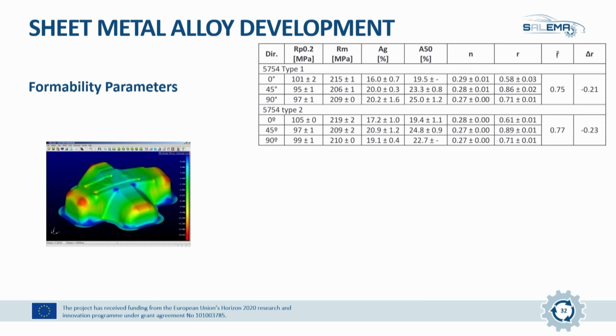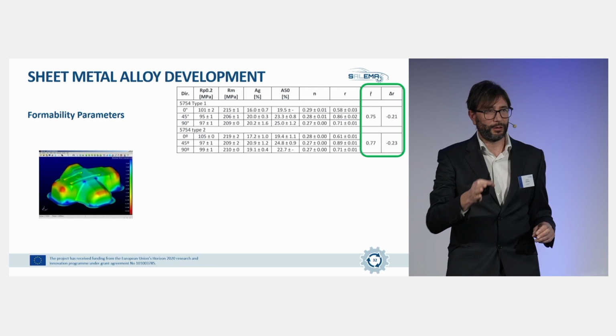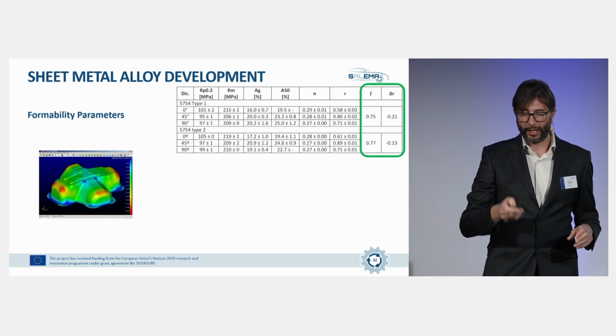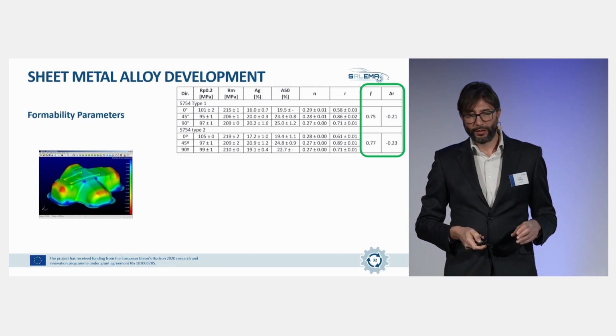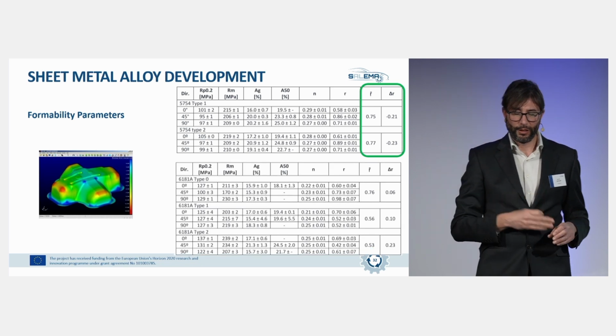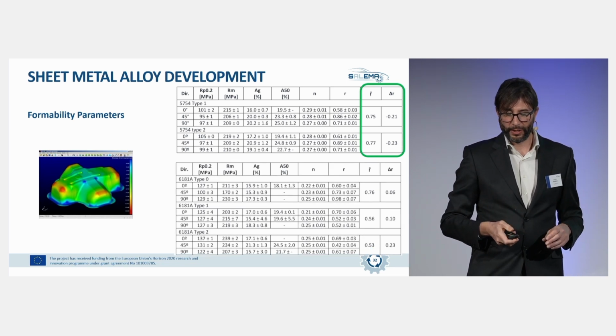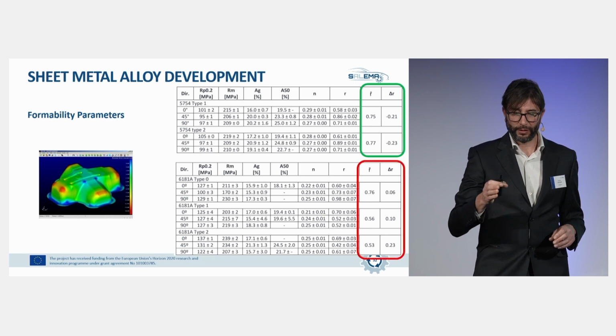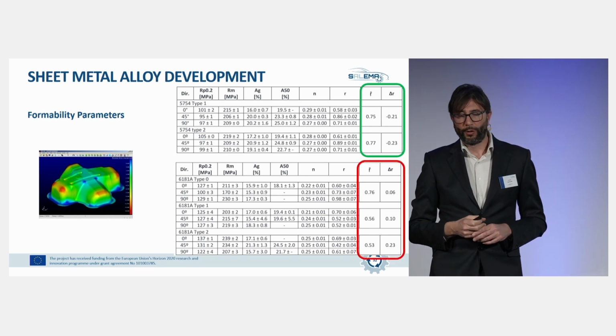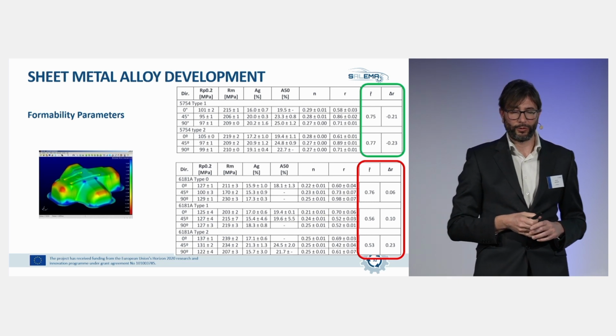But once we look at the formability of those alloys, we had a small surprise. So for 5754, where only iron needed to be slightly increased, almost no difference was observed in formability, and the formability parameters remain the same. But for 6181, we observe a pretty big change in the formability parameters and a reduction by increasing the amount of scrap.